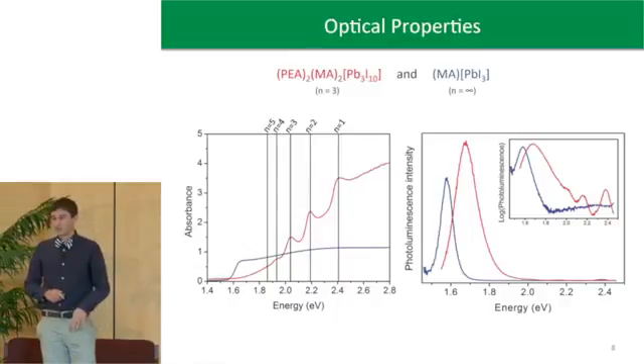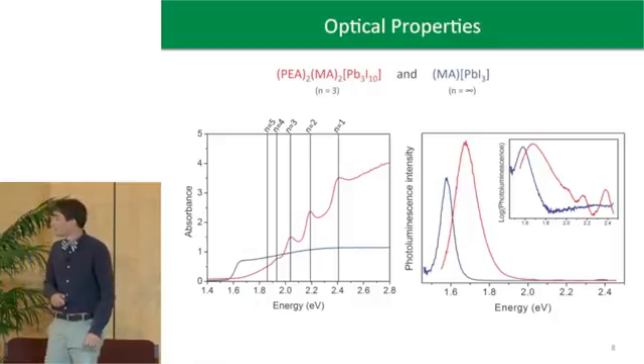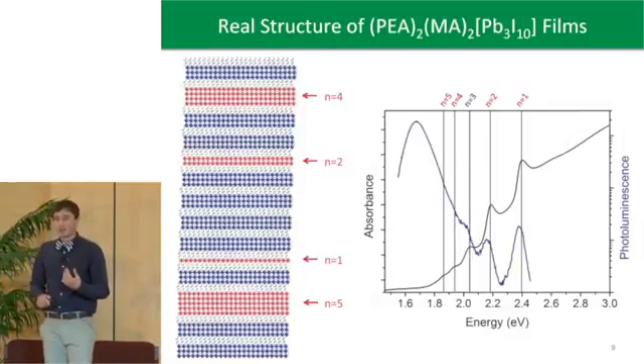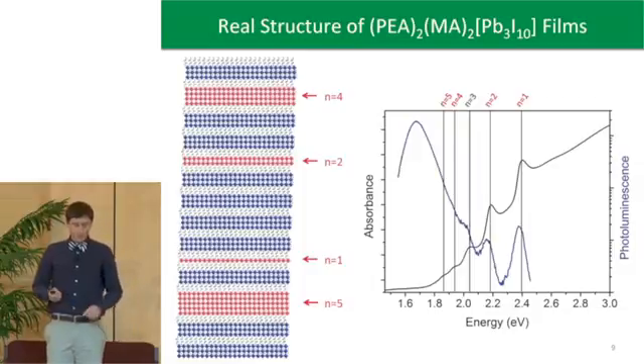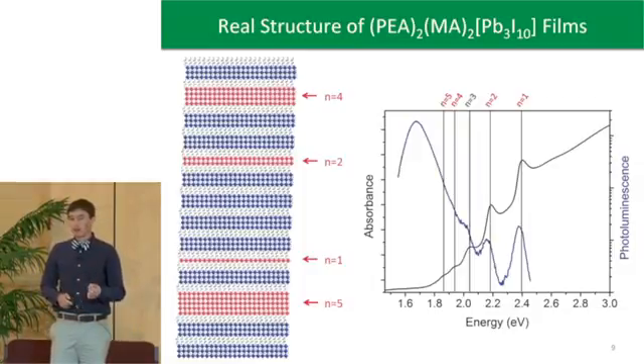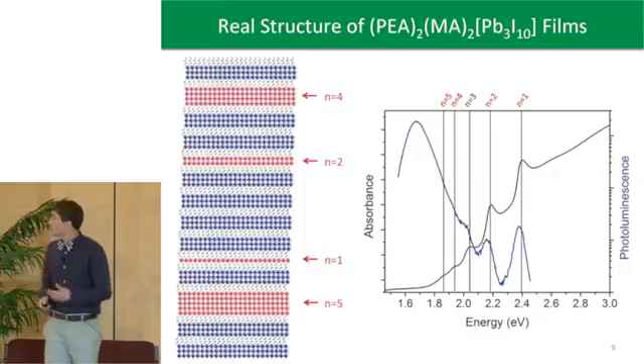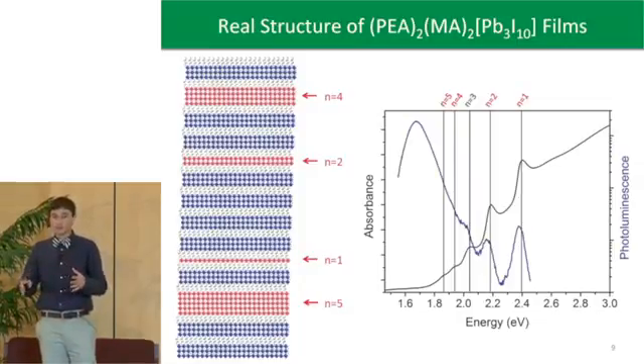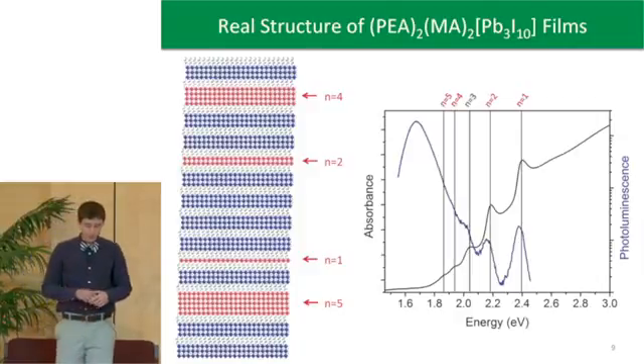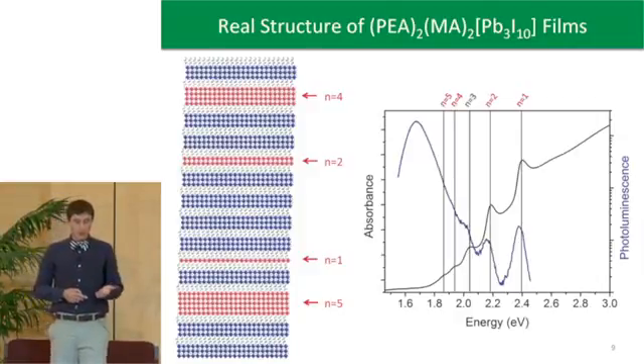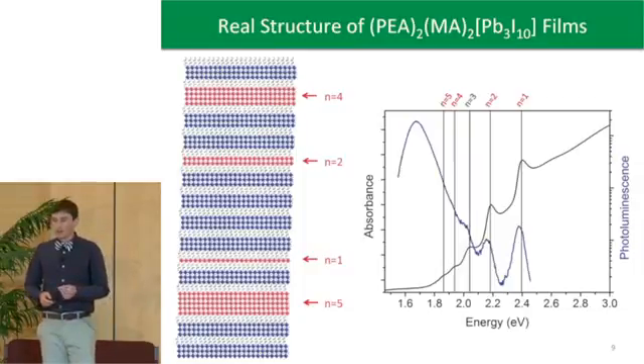We do think it probably still is a layered perovskite, but it's not exactly the layered perovskite that we were searching for. So this is what we think is actually happening during film formation. Once you deposit the film down, we have large domains of N=3 material, the blue octahedra up there. And these are large domains that will diffract X-rays. So we were able to take X-rays of these materials and confirm that it is exclusively N=3 crystalline material by X-ray. However, defect layers of the N=1, 2, 4, and 5 are in the film.